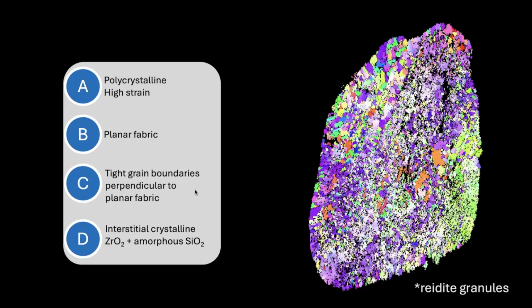And then the interstitial crystalline zirconia and amorphous silica also makes sense because this is another phase diagram. If you start with a zirconium silicate and you go to higher temperatures, you start making combinations of crystalline zirconia plus a silica-rich liquid. Eventually you get to liquids, but that's all the way up here. These are really high temperatures. So something like this, something like this, something like this makes sense. To melt a cubic zirconia, you would need a very, very high temperature. So it kind of makes sense that we now would have an amorphous silica and a crystalline zirconia. It also makes sense that that would be interstitial to the granules because it should have been hotter there.